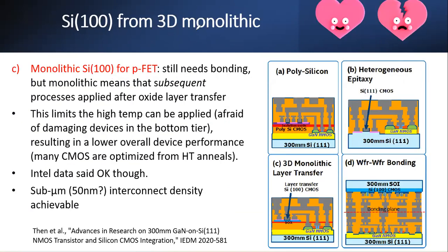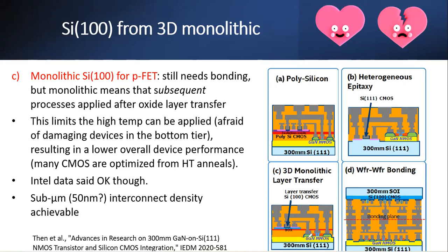So the 3D monolithic, okay, is that okay? 3D monolithic is this case, which means that you build your N first, and then you layer transfer using an SOI or something. Then you start to grow your epi silicon, or your device, on top. You still need bonding. And then you perform the subsequent processes after oxide layer transfer.